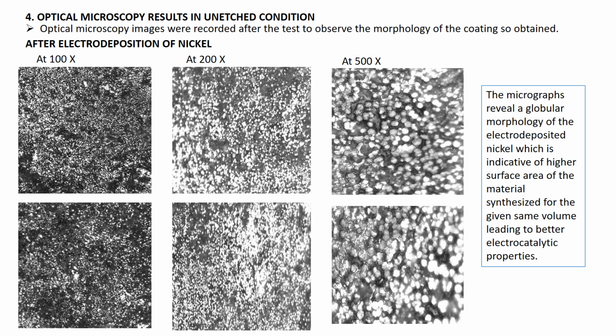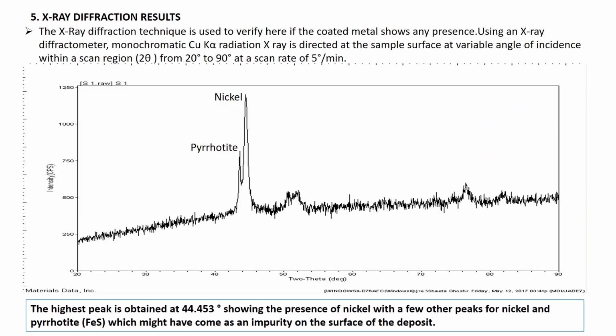These are the optical microscopy results in unetched condition. These micrographs reveal a globular morphology, which indicates that a higher surface area of the material is synthesized for the same volume, leading to better electrocatalytic properties. And the XRD results here show that the highest peak is obtained at nearly 45 degrees, showing the presence of nickel, with a few other peaks of pyrrhotite, which may be present as an impurity on the surface of